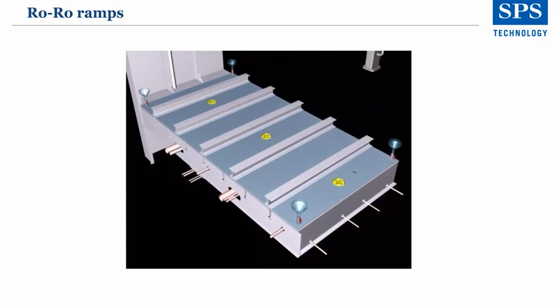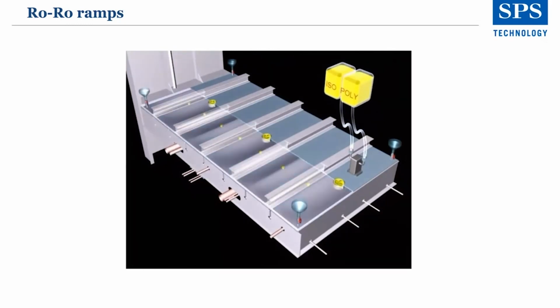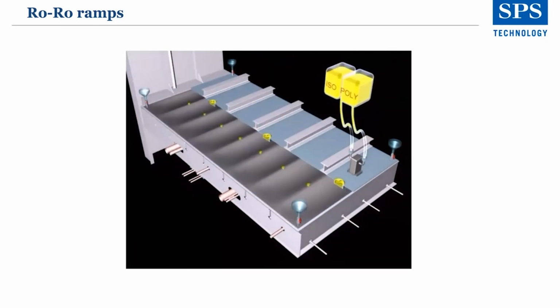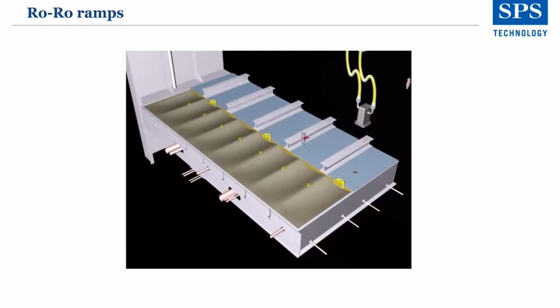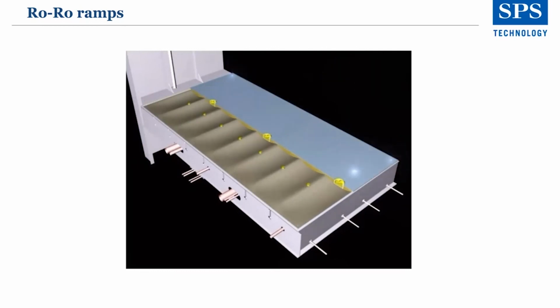A two-part chemical mixture is mixed at the lowest point of the cavity. Once it enters the cavity, it takes a few minutes to fill, and then after 10-15 minutes, it solidifies, bonding the new top plate to the old worn bottom plate. In some cases, the old worn bottom plate has corroded down to 50%,